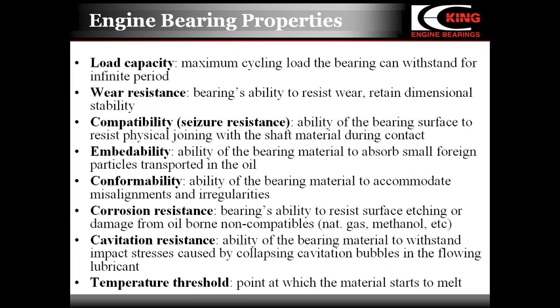At last, temperature threshold — the temperature at which bearing material starts to melt. I would like to draw your attention to the contradiction between the required bearing properties. Load capacity, wear resistance, and cavitation resistance are properties that refer to material strength and hardness, whereas compatibility, embedibility, and conformability characterize the bearing material softness. So the bearing material should be both strong and soft. It sounds paradoxical, but all existing bearing materials are designed to combine those contradictory properties with a certain compromise.